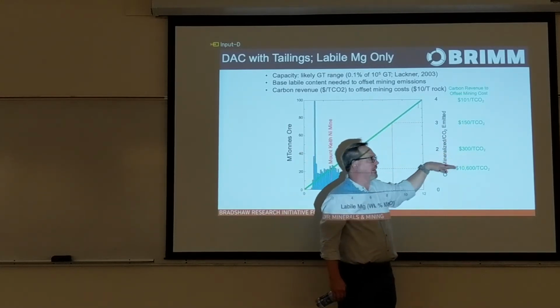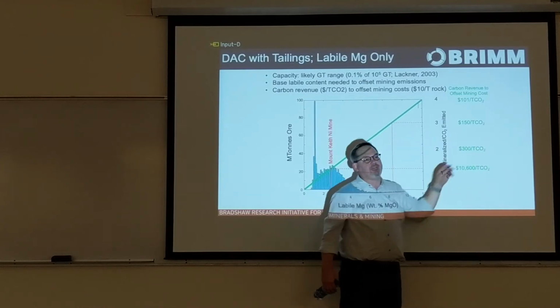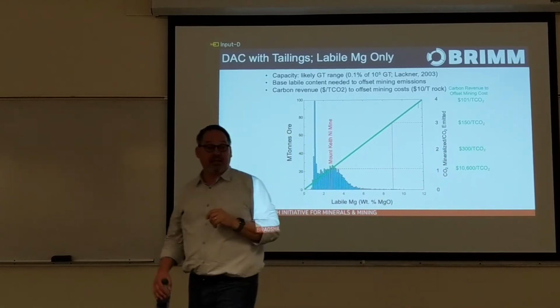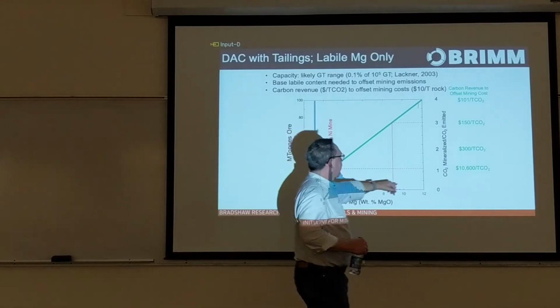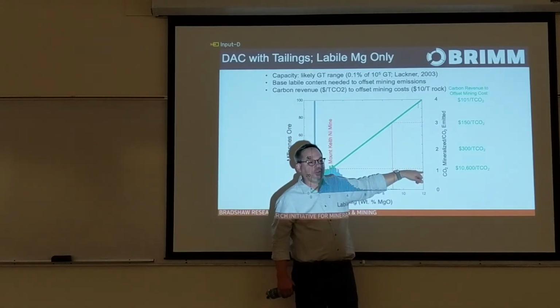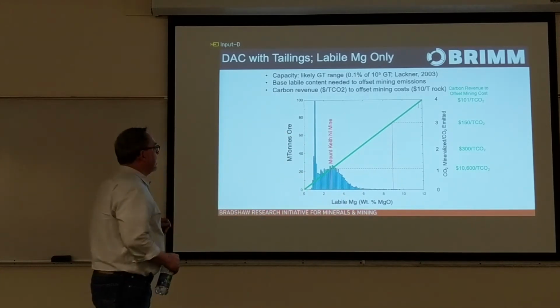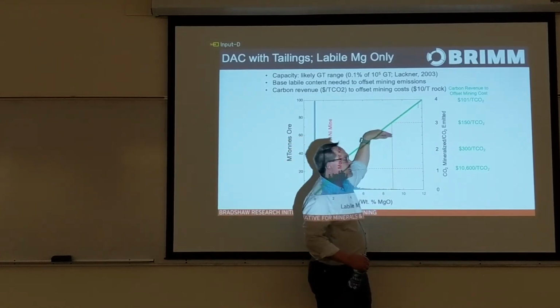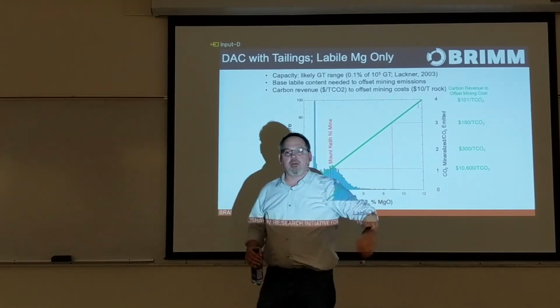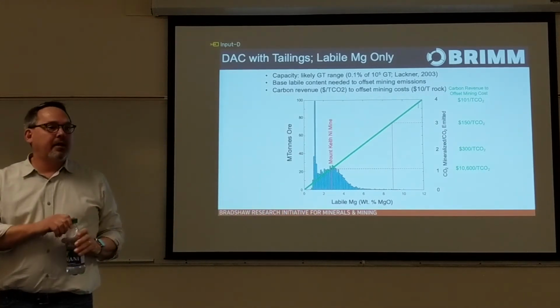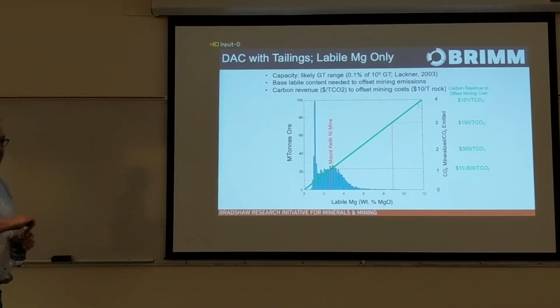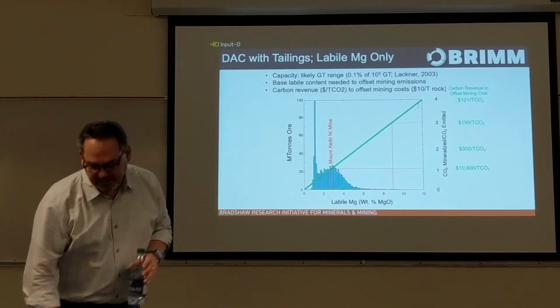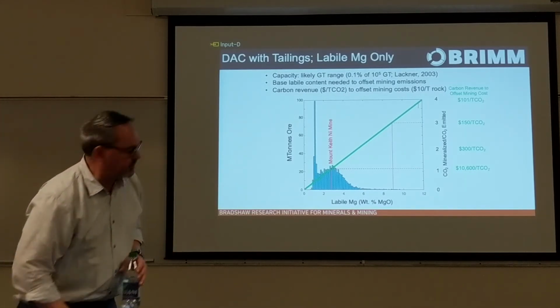And then if you assume a $10 a ton open pit cost for mining, you can calculate what the carbon tax would have to be to pay for mine operations. And that goes to infinity as you approach 1, because you offset all of your mine emissions first before you can take a penny from the carbon tax. So when you get out into these regimes up in here, you're paying for your entire mine operations with the carbon tax. There's no commodity or luxury good that you're extracting from the mine as part of the process. So it's hard to get beyond hundreds of dollars per ton.